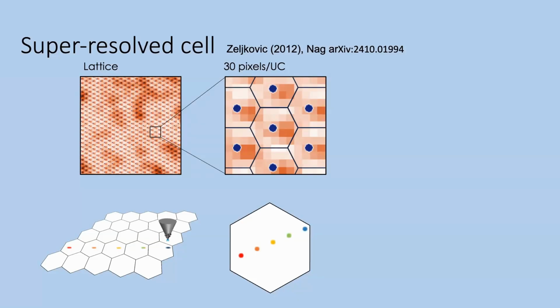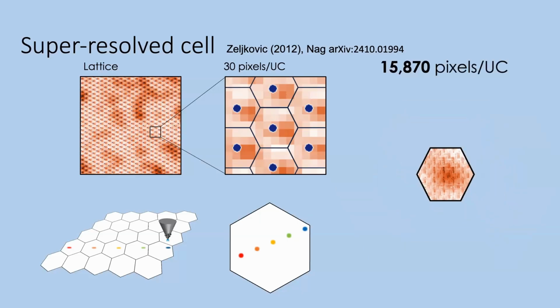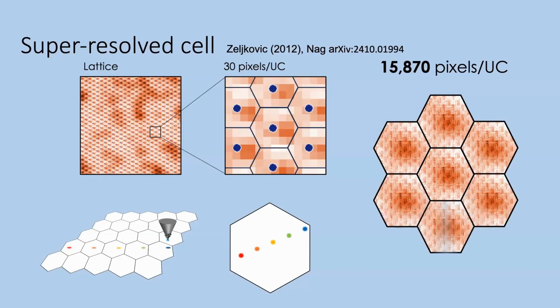So as long as we are able to define the lattice over this grid, we can collect these different points that we probe the unit cell within, into a super resolved single unit cell. So instead of having very lousy resolution per unit cell, we end up with a single unit cell that now has thousands of pixels collected from throughout the field of view. And now we can resolve very carefully the distribution of the wave function within a single unit cell. This works as long as all the unit cells are identical, so we need to find regions with sufficiently low disorder, where everything is uniform enough for this analysis. Drift should be minimal for this analysis to work. So now I just copy this single super resolved unit cell 6 more times, and we can see the periodicity of the wave function across the lattice.